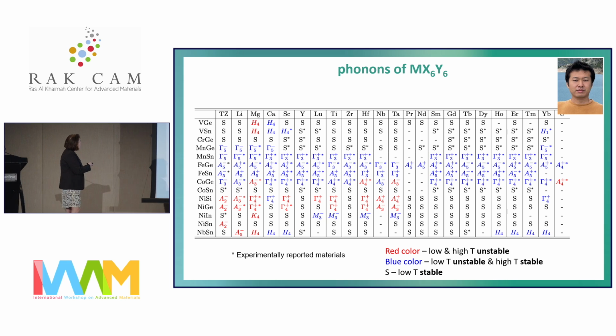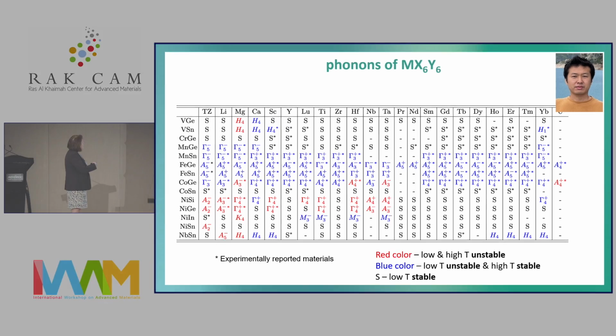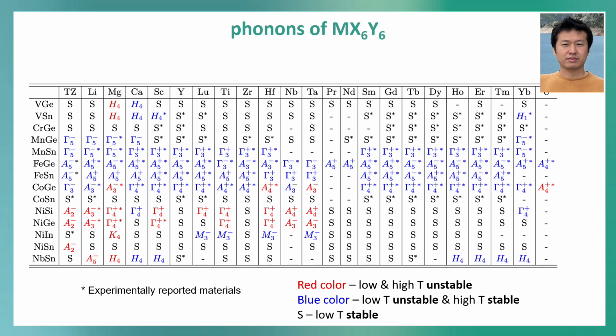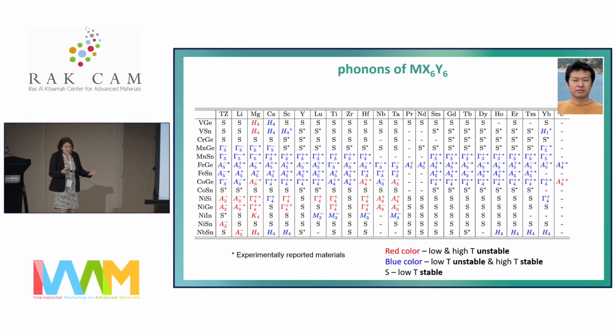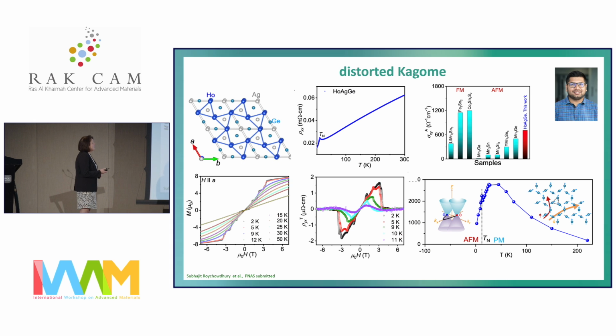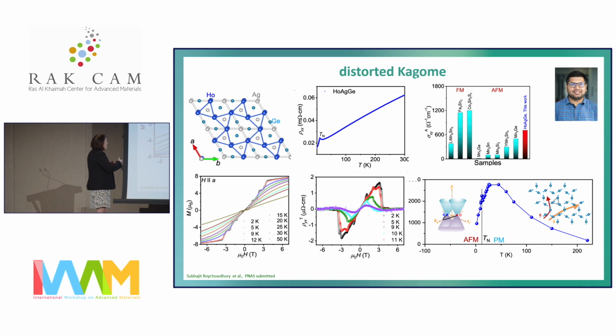Because now you can combine all these transition metal main groups with all these compositions of alkaline earths and rare earths and so on. So you have many possibilities. And all the red ones show they are unstable at low and high temperature, and the blue ones are where we expect a certain charge density wave and electronic instability, and eventually superconductivity. So Subhajit, as a farewell present, gave me another system, so it's not only the 1,1 composition and the 1,6,6 composition. I think this family is infinite.